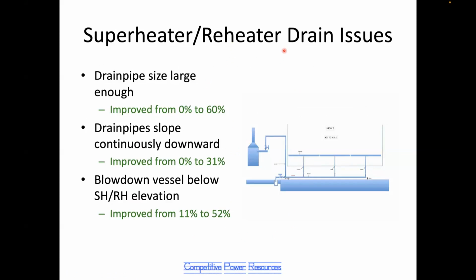Some of the design issues that have caused superheaters not to drain properly: if the drain pipe size is too small, the water can't flow through the small pipe rapidly enough to remove all the water before the steam flow comes. In 2008, all of the drain pipes were too small on the boilers we looked at. Now, over almost 20 years, that has improved. And 60% of them now have large enough drain pipes. So people have learned from the mistake of putting in drain pipes that are too small.